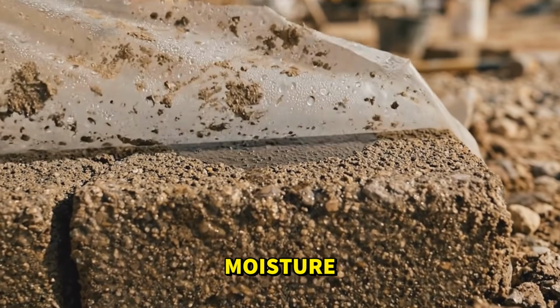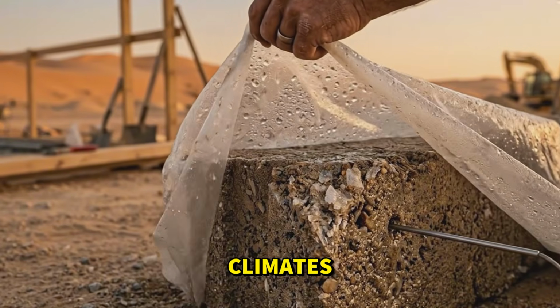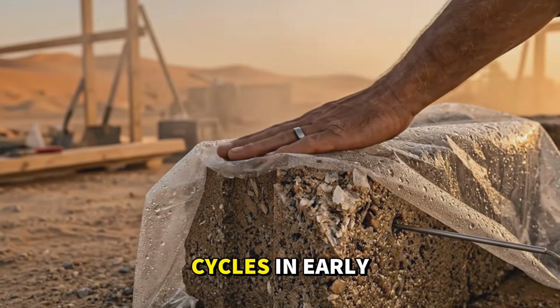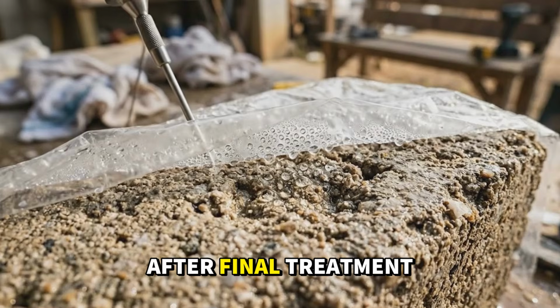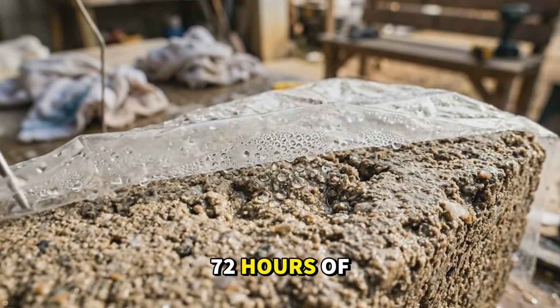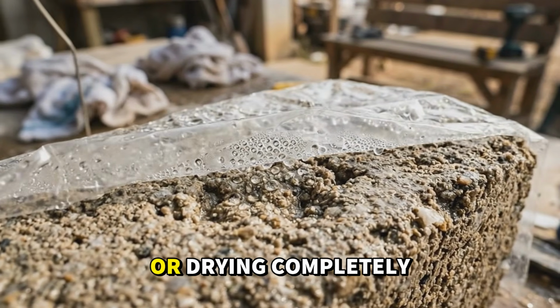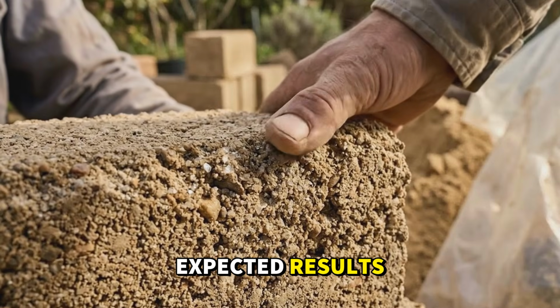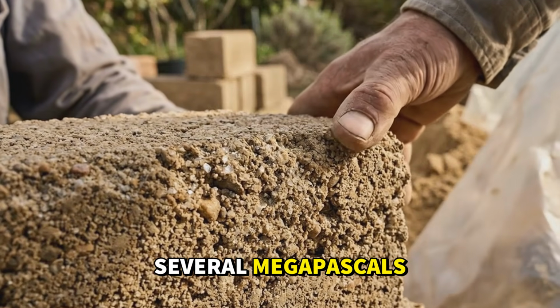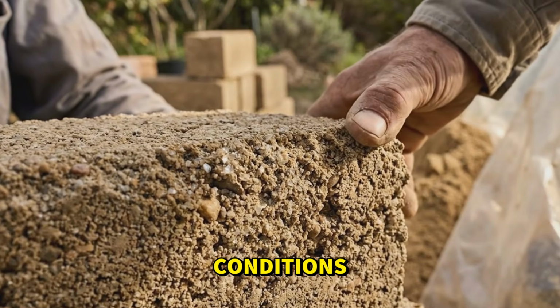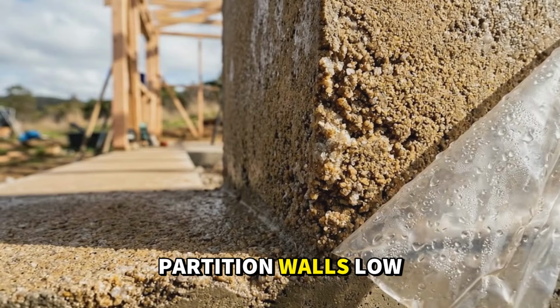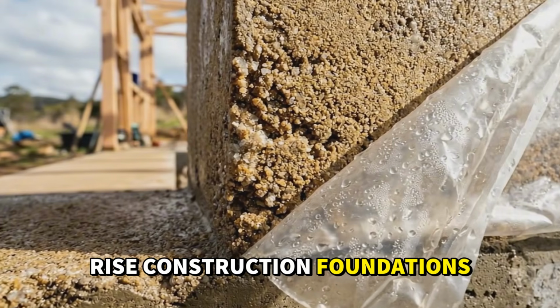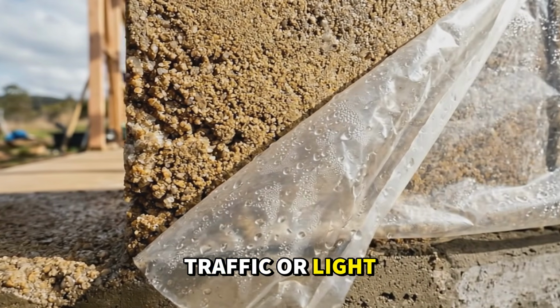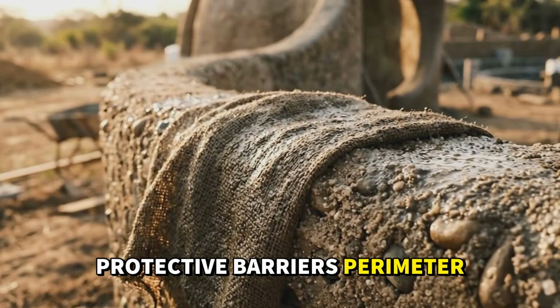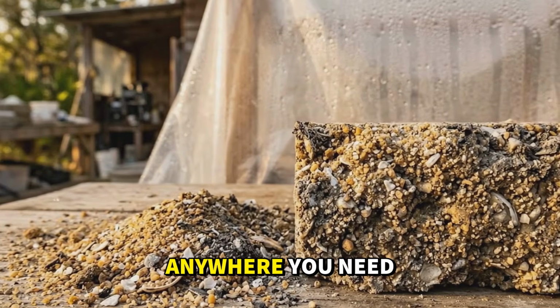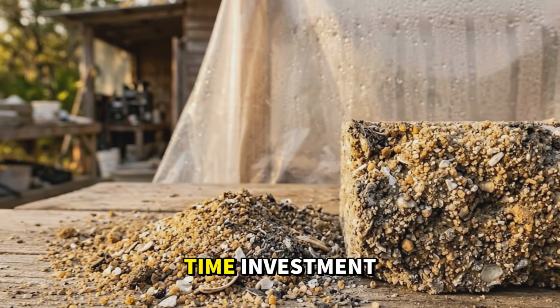The bacteria need moisture. If you're working in hot, dry climates, shade the work or apply treatment cycles in early morning and evening. After final treatment cycle, allow at least 72 hours of moist curing before exposing to load or drying completely. Expected results. Compressive strength of several megapascals with adequate treatment cycles in good conditions. Suitable for non-load-bearing partition walls. Low-rise construction foundations, paving for foot traffic or light vehicles, protective barriers, perimeter walls, garden structures. Anywhere you need solid material and can accept the time investment.